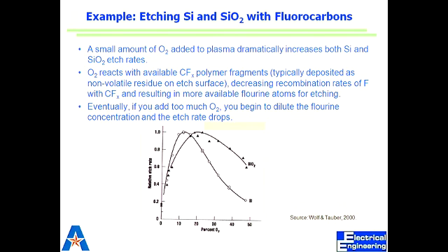Okay, so it means that the maximum is reached when oxygen is 20% by concentration. After that, the etch rate drops. So if you add oxygen, the F by C ratio increases, but you cannot add oxygen more than 20% by concentration in that chamber.